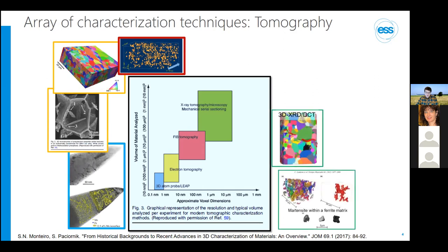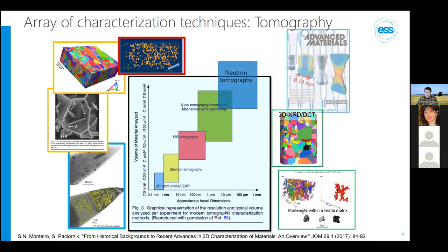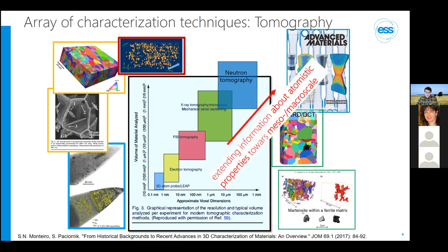X-ray and synchrotron tomography can investigate larger samples with sub-micrometer resolutions and can, for example, visualize individual grains in polycrystalline samples. Now, neutron tomography offers spatial resolution starting beyond 1 micrometer, but allows to study much larger samples. In particular, it allows to extend the information about atomistic properties towards the meso and macro scale.